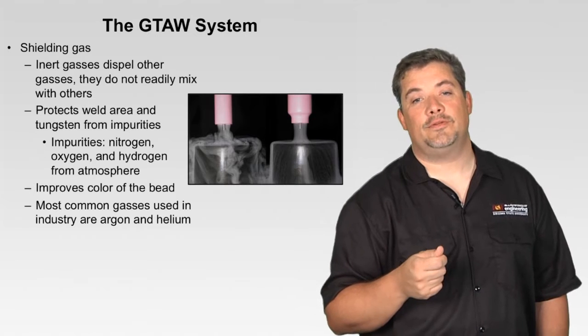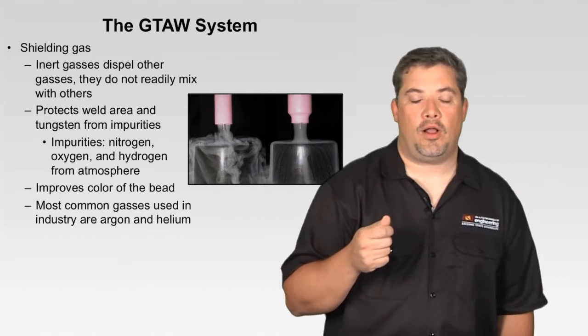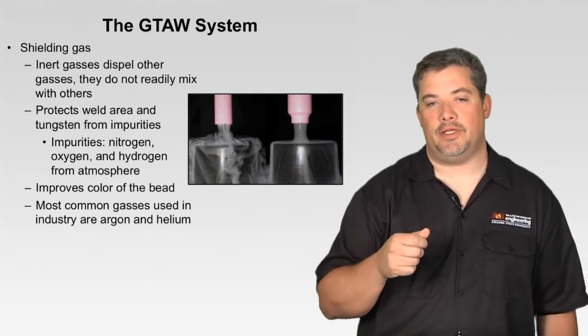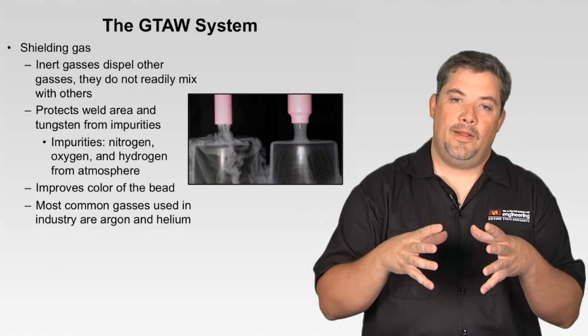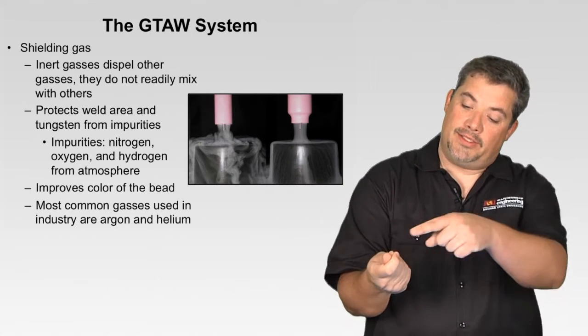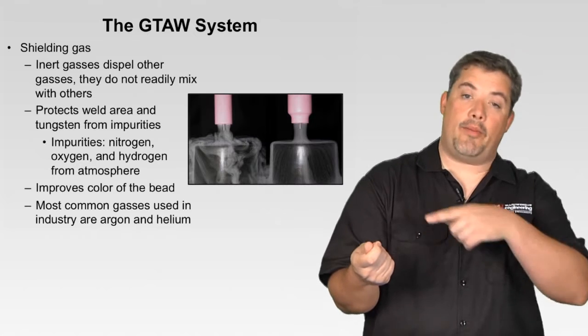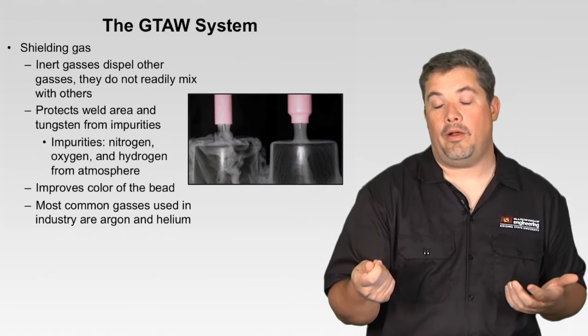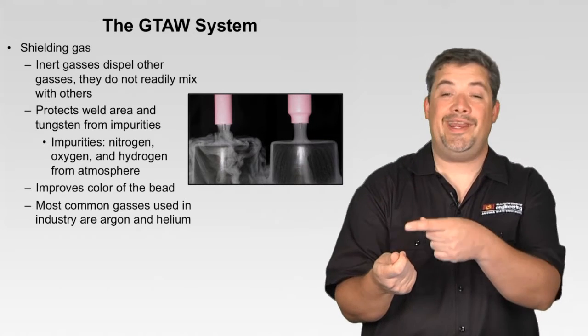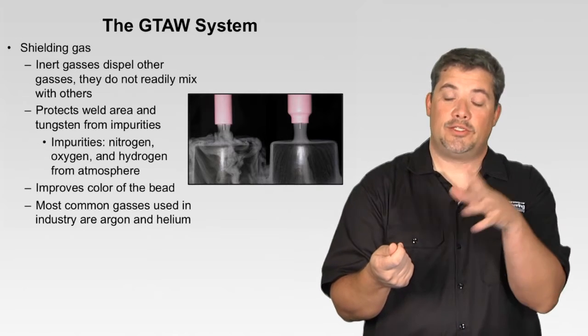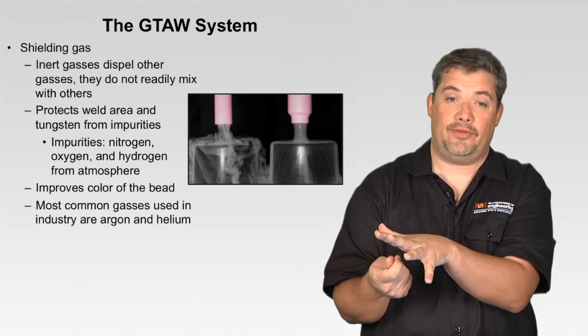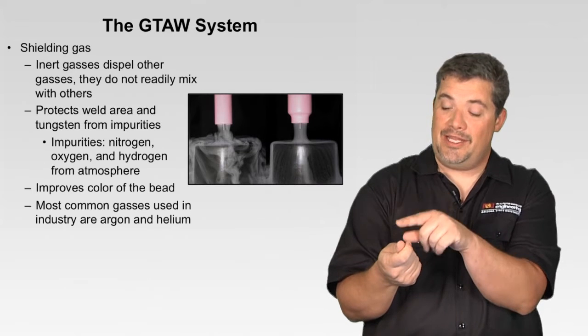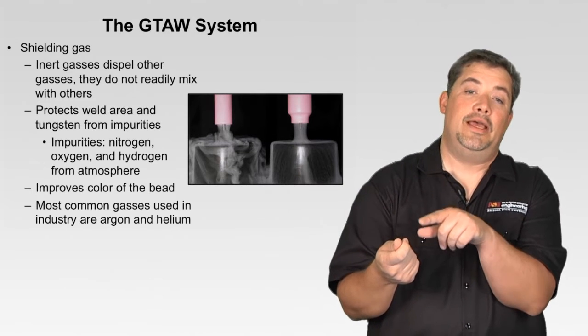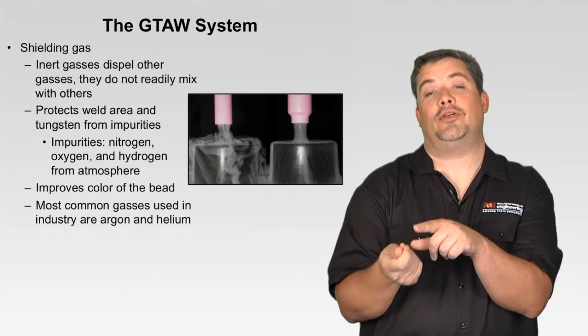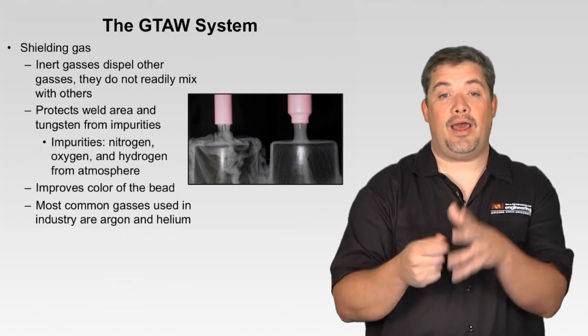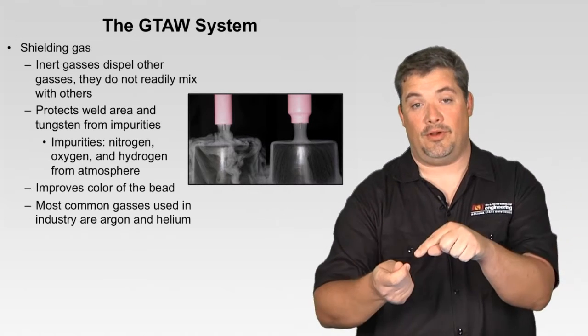The shielding gas improves the color of the weld bead. A common misconception in the welding world is that you can look on the back side of your weld and see that there's a color change and say, oh, I got penetration on that part. Well, how did you really? All that tells me is that you heated the back side enough so that the atmosphere attacked that surface and oxidized it, and each different shade of color tells you what temperature the surface of that material was when it got out of that argon environment and the atmosphere attacked it.